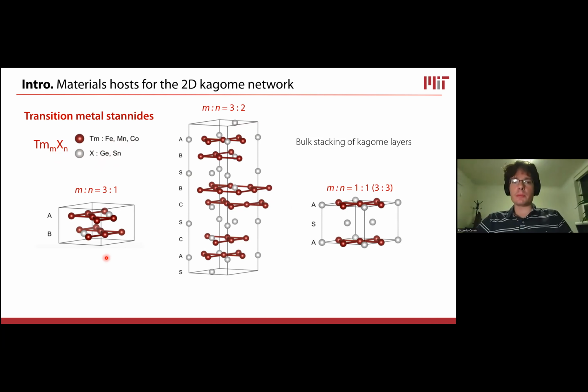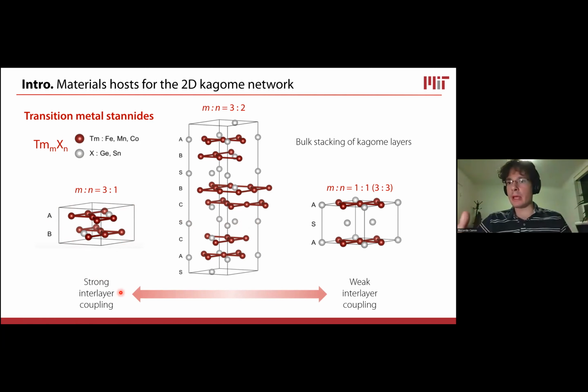And what you can do structurally, by changing the stoichiometry or the ratio between the number of Kagome layers to the number of stannide layers, which are interleaved between the Kagome layers, is tune the dimensionality of these Kagome systems from being more three-dimensional, the limit where you have strong inter-Kagome layer coupling, and this is the limit where you only have Kagome layers facing each other. So you have Kagome, Kagome, Kagome, basically a repetition of Kagome layers, to the two-dimensional limit where you have the Kagome layers being isolated and separated out by a layer of stannide.